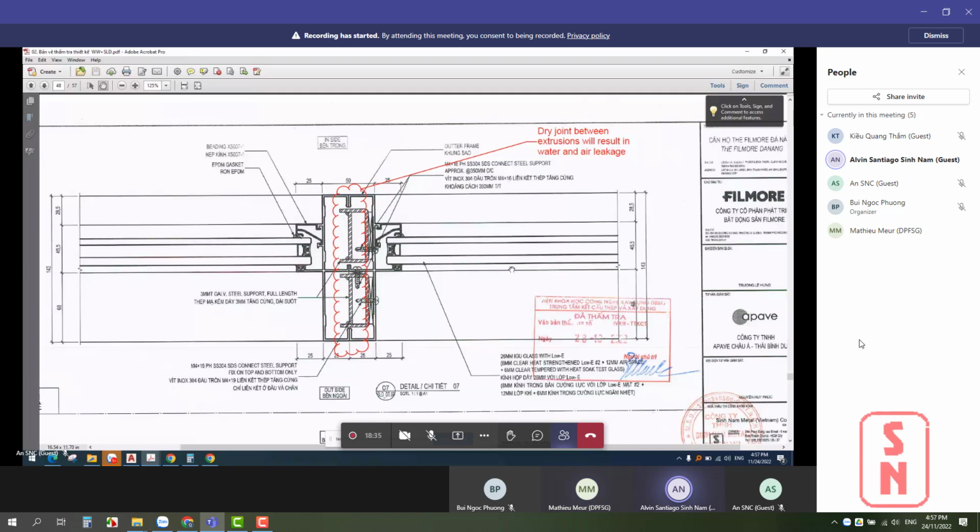Yes, the insides of our profile will be chromate, but we'll add shimming in between the two metals. It doesn't have to be thick shimming. It can even be just a polyethylene tape or something like that, just enough to prevent direct contact. Understand. Whatever is easier for you. Thank you.